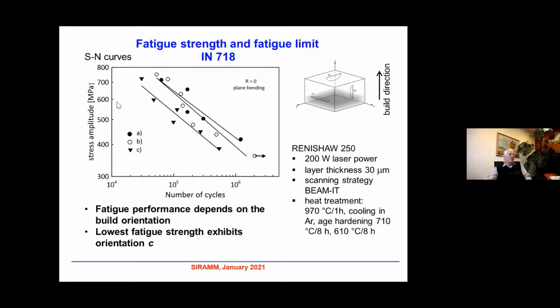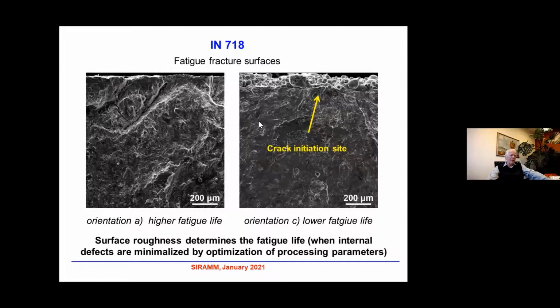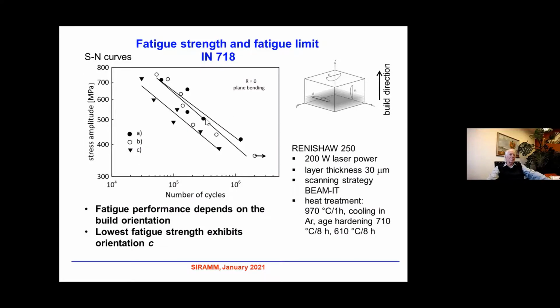And again, S-N curves or results. And you can see that for pure plane bending, the result is very, very similar. Again, orientation A and B is better than orientation C. So it depends predominantly on the quality of the surface, and this has to be simply taken into account. If you imagine a component with internal features, which is loaded by cyclic loads, it can play a role because the lifetime can change by 1 order of magnitude. Here you can see fracture surfaces of specimens which were presented here.